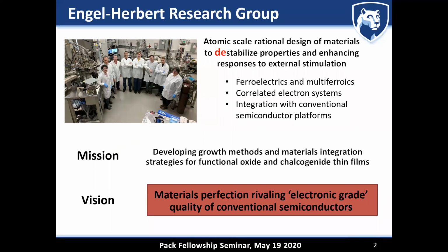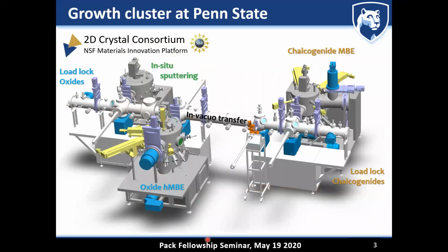So to give you a little bit of an idea of what the capabilities are in the lab, we have a relatively large MBE cluster at Penn State. Just to give you an idea, we have 2 MBE systems. These are 2 molecular beam epitaxy chambers in which we can evaporate elements from effusion cells to then grow a film. And so we can do this for the chalcogenides. So everything that has selenium or tellurium in the compound can be grown here in this chalcogenide system.